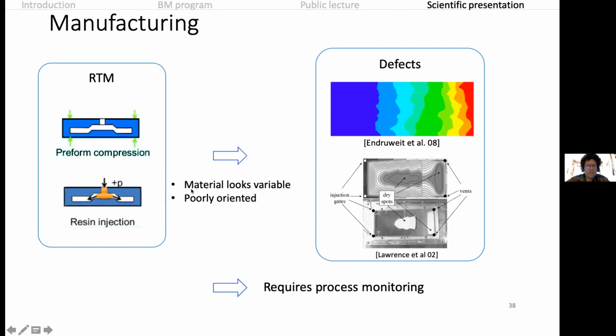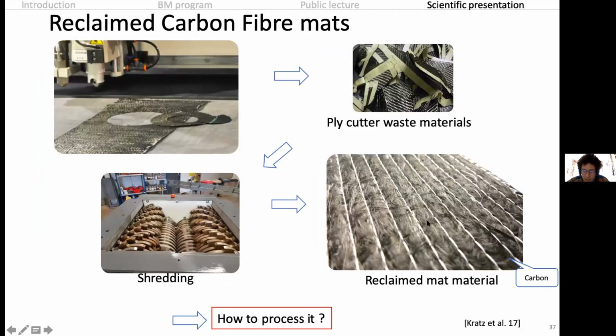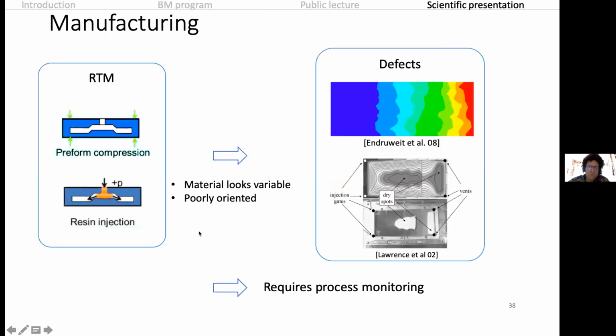The problem is this reclaimed material looks very variable. You see, the fibers are really randomly distributed in the roll here. So you have something that's very variable, and it looks poly oriented. And what we found is that if we inject resin from one end here and hope that the resin flows and fills the mold homogeneously until the end, well, this is not true.